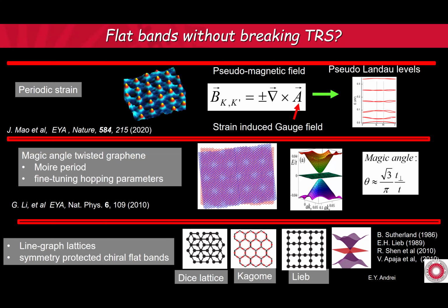Maybe just a comment. There are known lattices where you can, with quite short range hopping, make the bands almost exactly flat. Even beyond the magic angle ones, there's some residual dispersion, right? Then, given that, you can ask what terms you would have to add to the Hamiltonian to make it perfectly flat. And it turns out that these are very realistic terms in some circumstances. But then you lose the topology, I think. No, you don't. These lattice models are topological also, basically Landau levels, so you can get bands that are exactly degenerate like a Landau level, yet only have hopping terms on a lattice to maybe second or third nearest neighbor to very, very good precision.